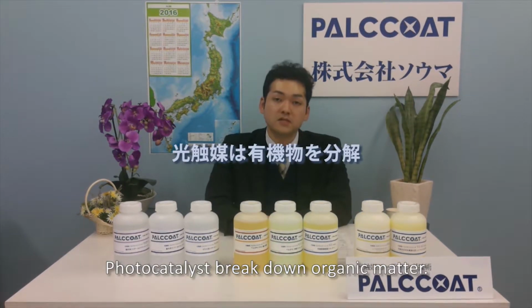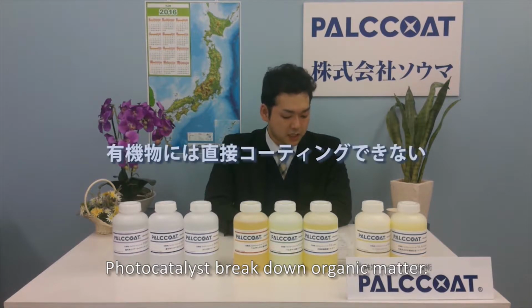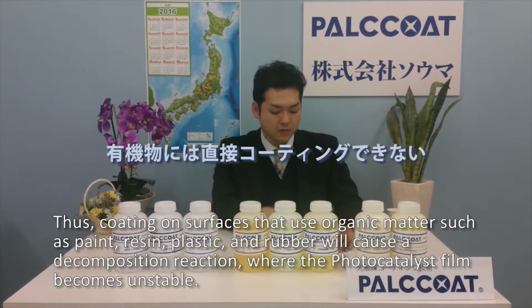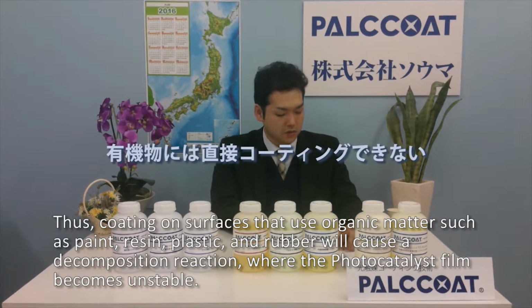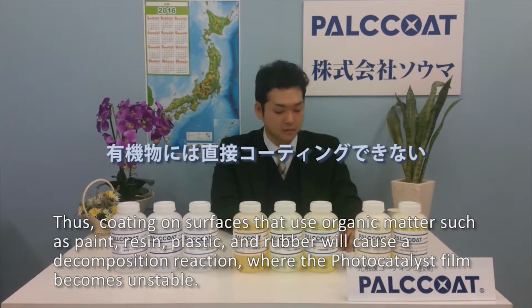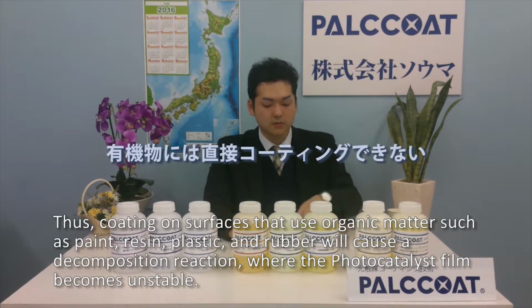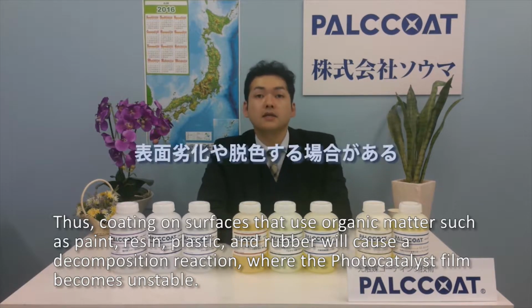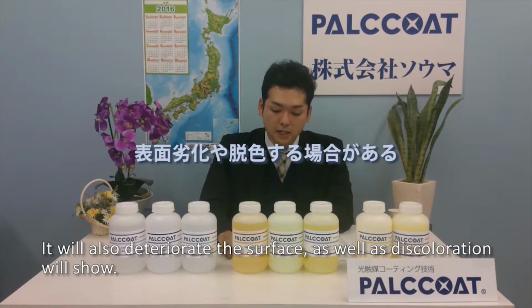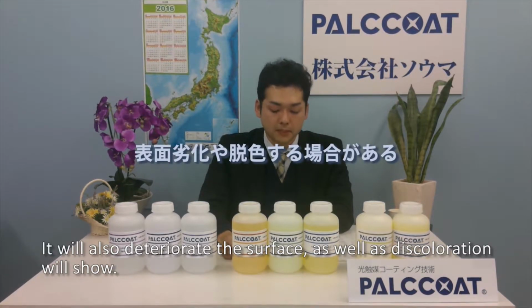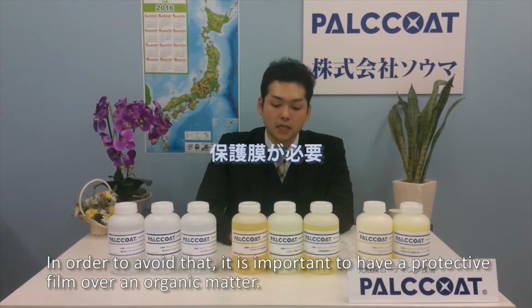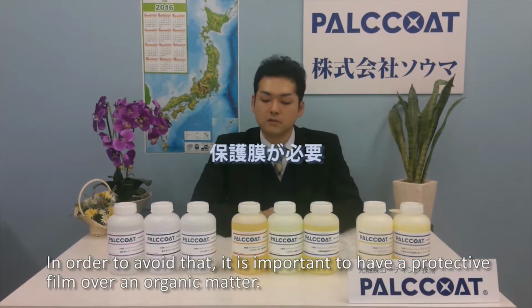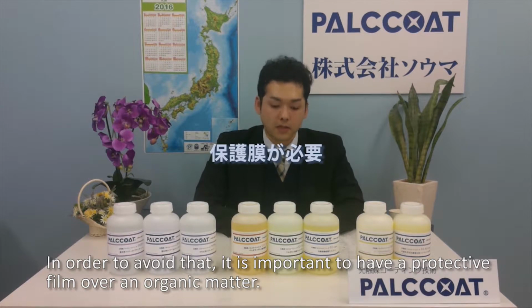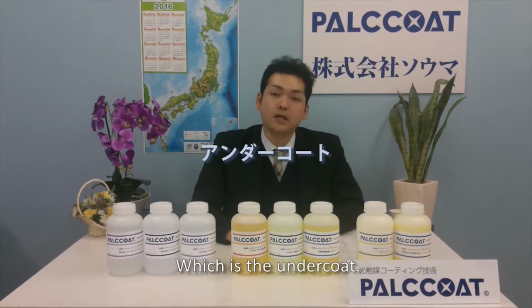Photocatalysts break down organic matter. Thus, coating on surfaces that use organic matter such as paint, resin, plastic, and rubber will cause a decomposition reaction where the photocatalyst film becomes unstable. It will also deteriorate the surface, and discoloration will show. In order to avoid that, it is important to have a protective film over the organic matter, which is the undercoat.